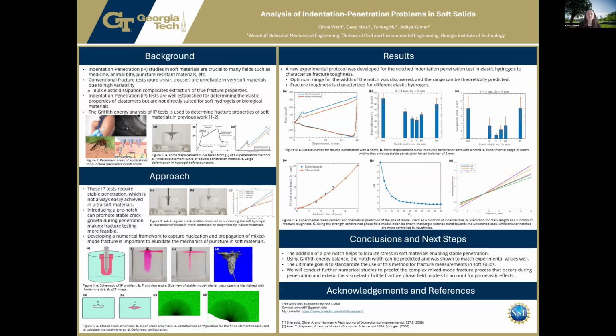To solve this, we introduce a pre-notch into the material before performing the penetration test. The idea is that the notch will act as a stress concentrator, and instead of cracks forming unpredictably, the notch localizes where the crack begins and promotes stable crack growth during penetration. You can see this concept illustrated in Figure 4, where we show the geometry of the indentation penetration setup, along with experimental images of controlled crack propagation.